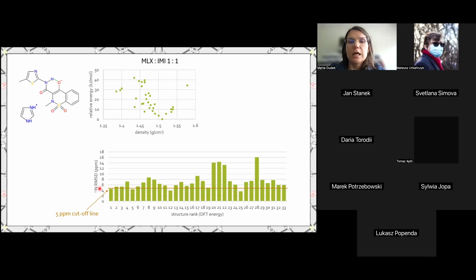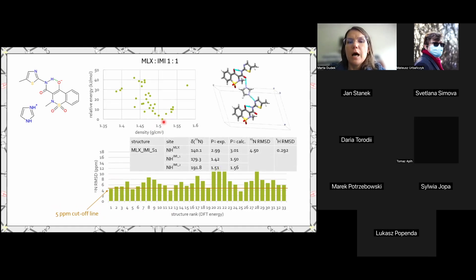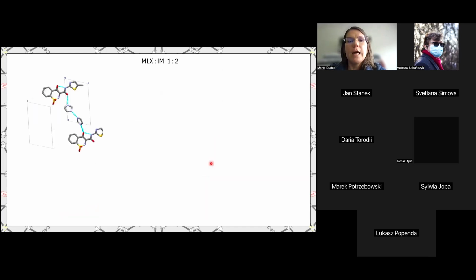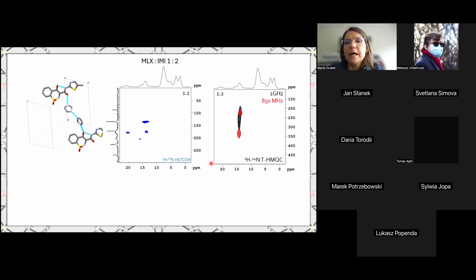Fortunately, they are very, very similar to this structure. This is one thing. And the other thing is that this structure here has very low energy, actually the lowest energy. So it corresponds to the real model in the best possible manner. So this is this structure here. And indeed, calculating it and comparing experimental and calculated PQ values confirmed this protonation state of meloxicam and imidazole in this crystal form. And finally, the last crystal form was also solved from powder X-ray diffraction without the protonation state. And we determined this protonation state using solid state NMR experiments.